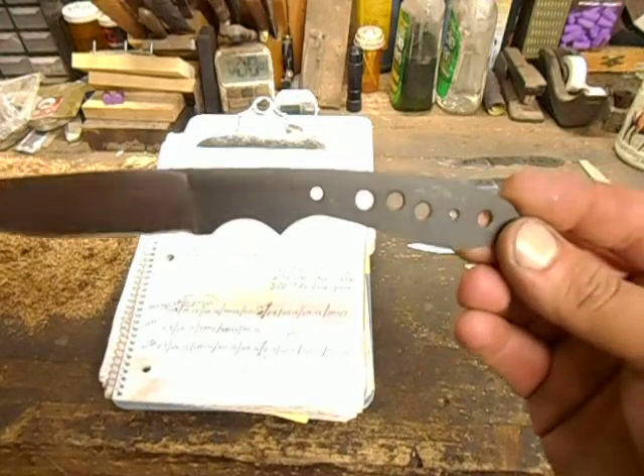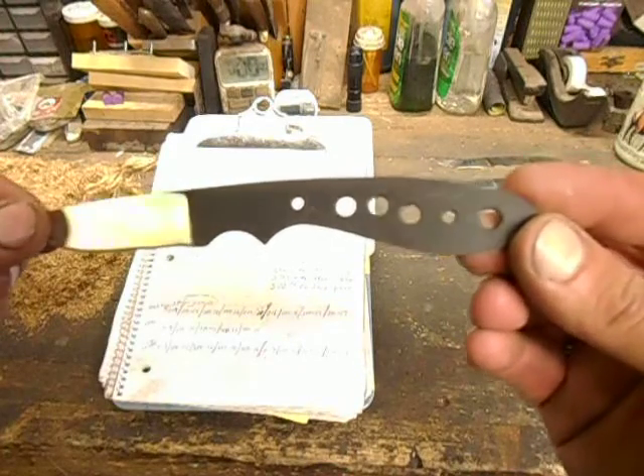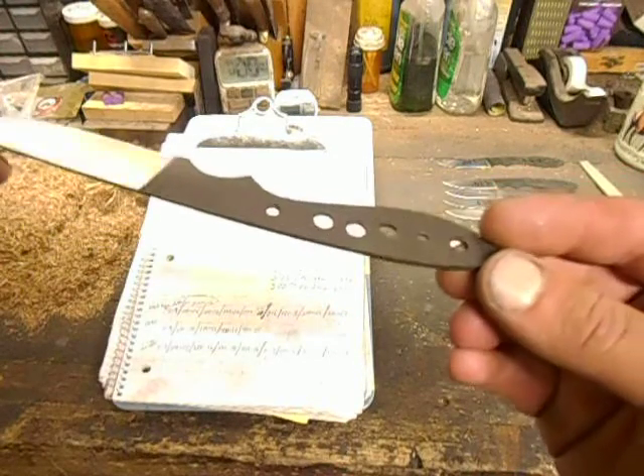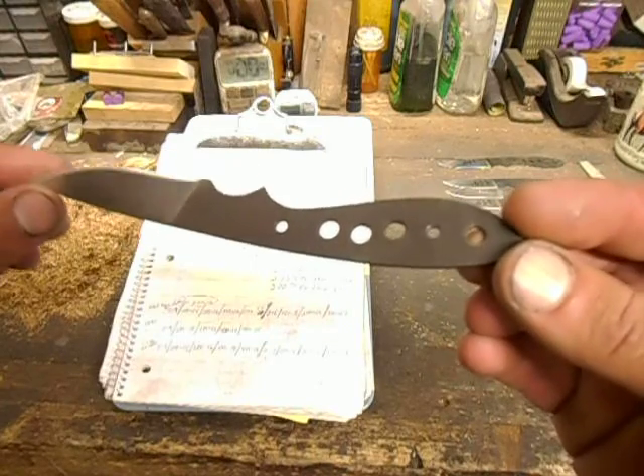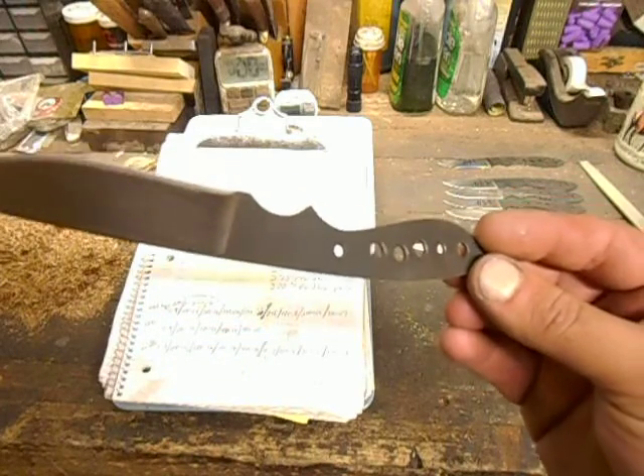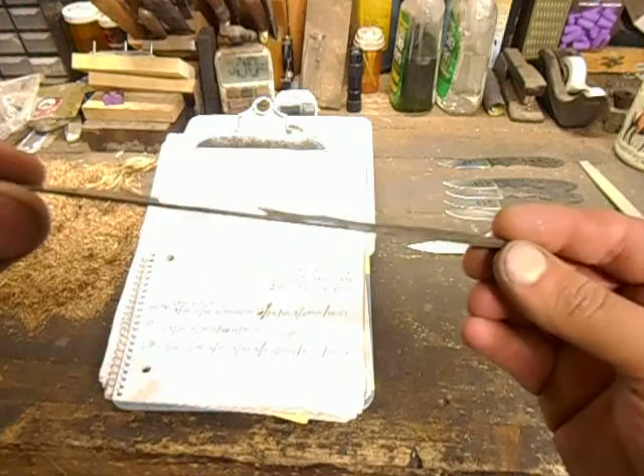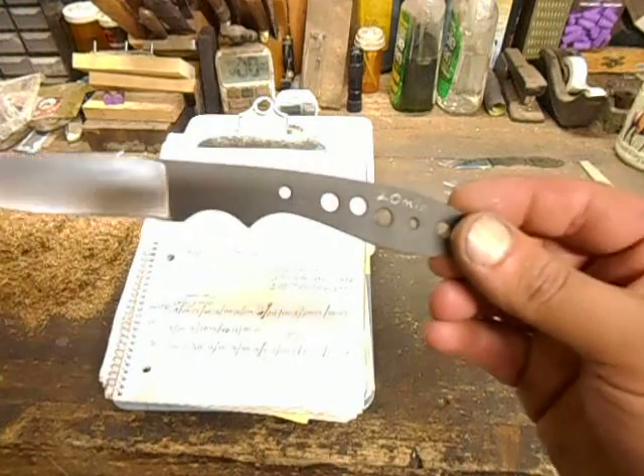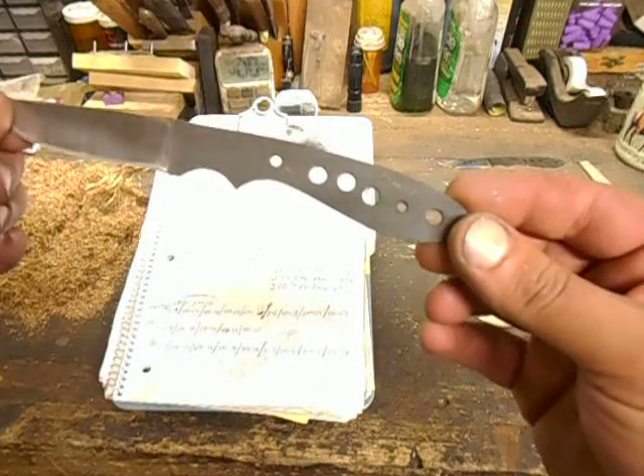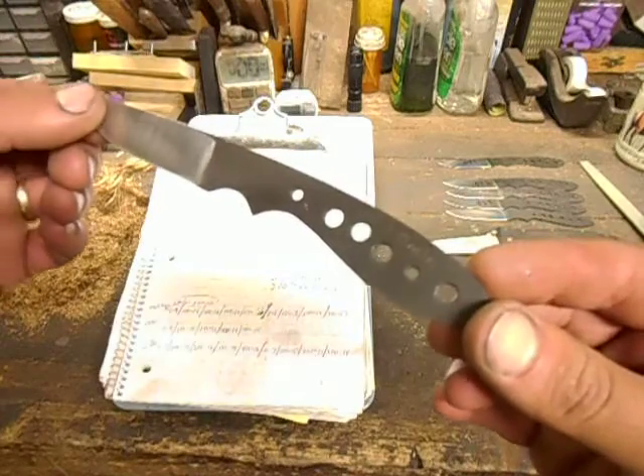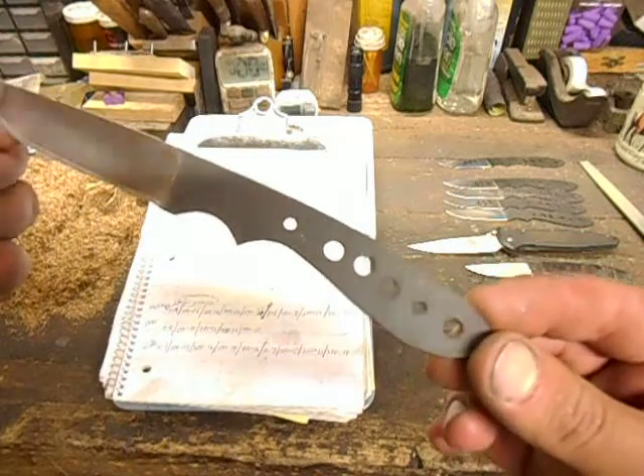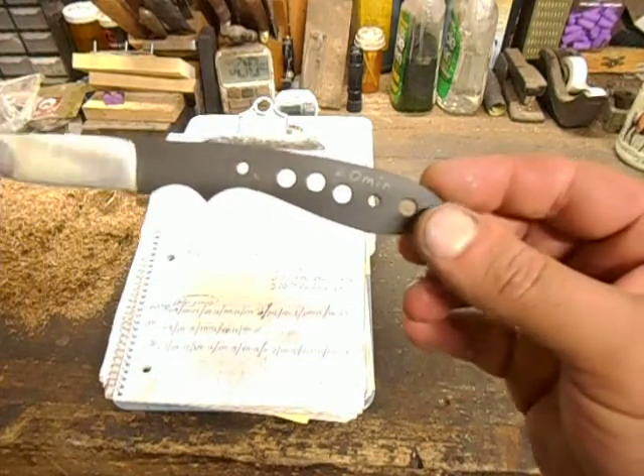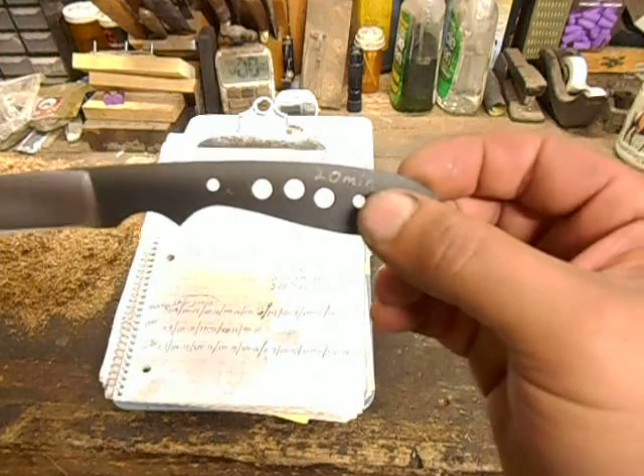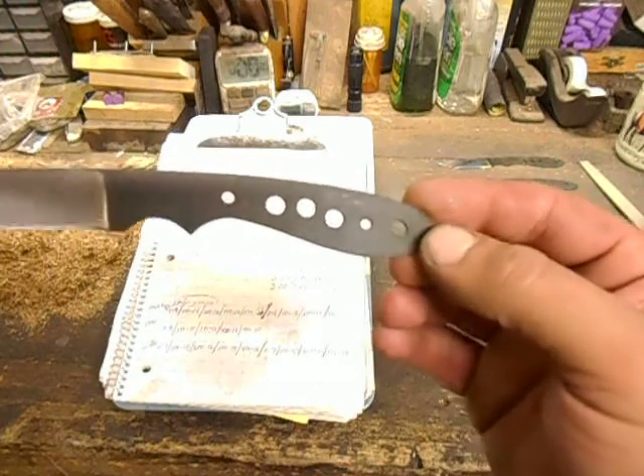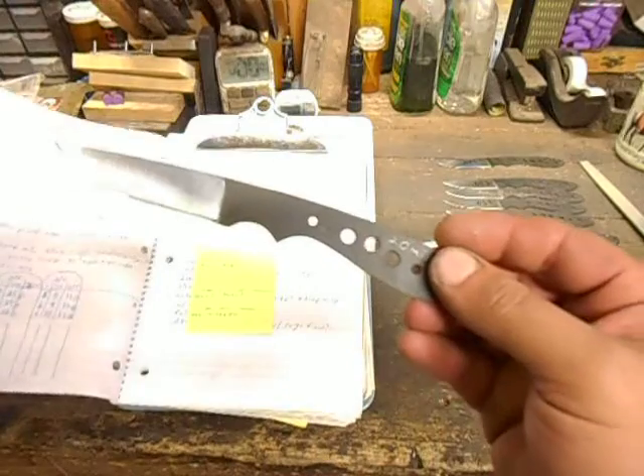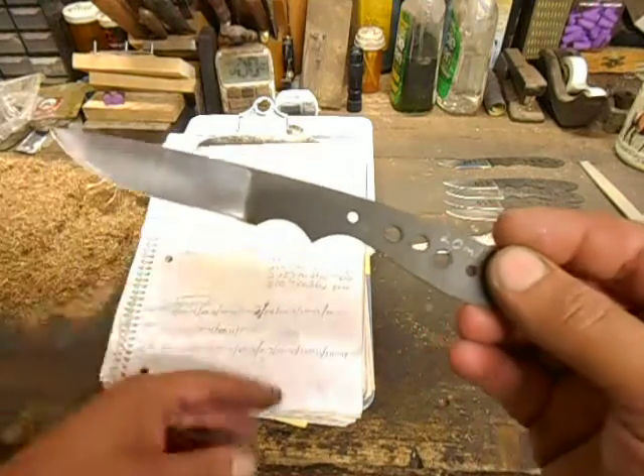I was envisioning large sheets of steel coming off the sides, and it didn't do that at all. Basically, it discolored it. And this particular one was in the 1900 degree kiln for 20 minutes and then quenched in 145 degree canola oil.